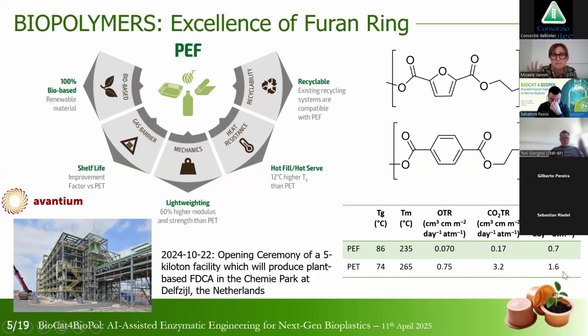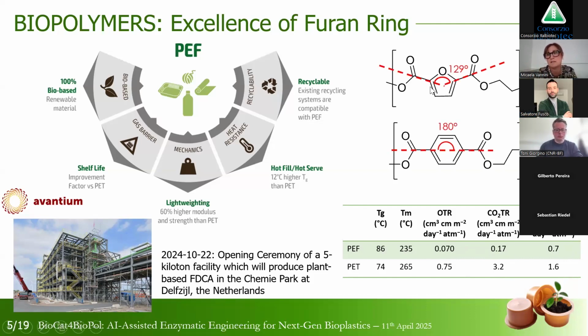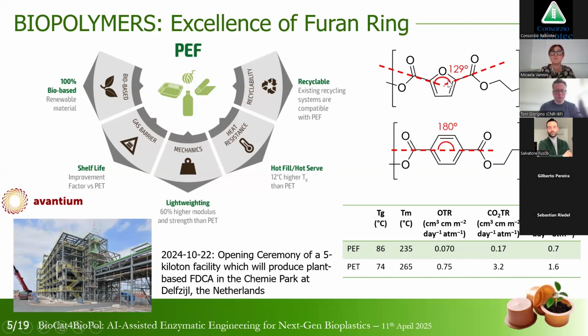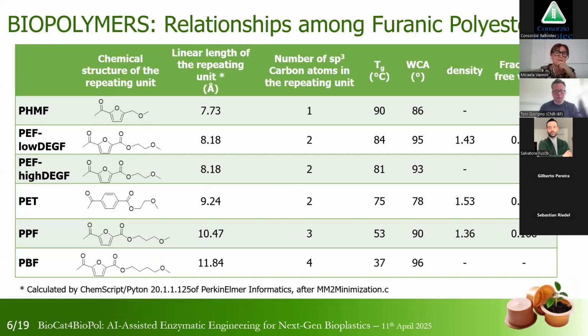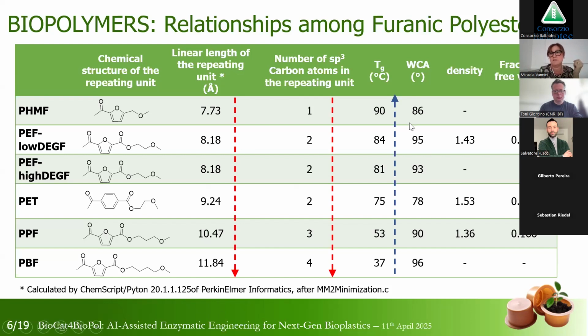These outstanding barrier properties are due to the lack of symmetry of the furan ring, which prevents the ring flipping along the macromolecular chain. But these incredible superior barrier properties are not only due to the rigidity. You can see the rigidity is evident also if we consider the glass transition temperature.